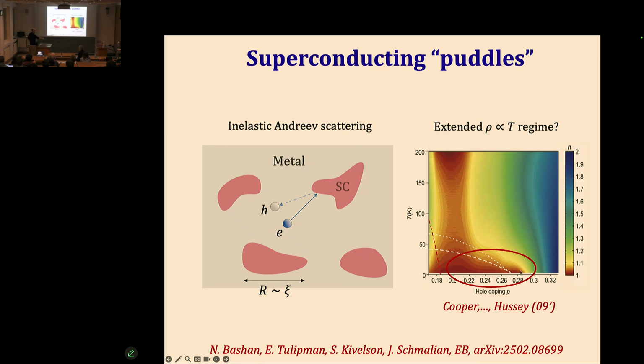Just to understand, what's the justification that the superconducting puddles are also in the hole-doped scenario? Sorry, let me clarify. This is all hole-doped. I'm actually not discussing electron-doped cuprates here. What I mean by overdoped or underdoped is that there's a maximum TC that occurs somewhere around 16% hole doping. Overdoped is basically beyond that. Underdoped is over here, which is not shown in this diagram. Still hole doped.